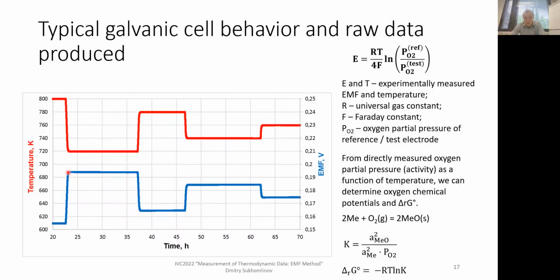And the EMF will be slowly approaching its stable value. And this stable value corresponds to equilibrium. With all this math we just discussed, it's going to provide us with the equilibrium oxygen partial pressure on the test side. Once we realize that this is in fact just a time series, we just keep collecting data every 5 seconds, every 10 seconds, depends how we want.